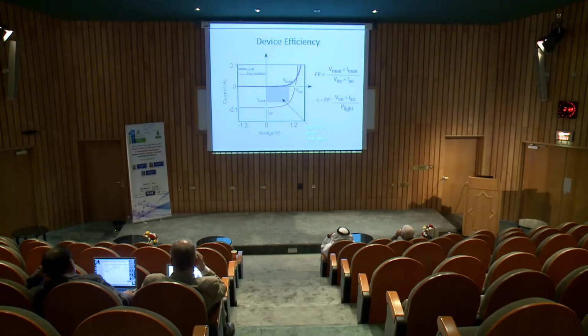After we make the device, this is how we characterize it. We measure the current as a function of the voltage. The blue curve is the current-voltage measurement in the dark. Then we illuminate the device with light and collect the photocurrent, which is the red curve. You can see the device efficiency is determined by a couple of parameters: the fill factor, and also the open circuit voltage, which is the maximum voltage generated by your device at zero current. It also depends on the short circuit current, which is the maximum photocurrent generated by your device under zero applied bias. And of course, if you shine more intense light on the device, you have higher efficiency compared to weak illumination.